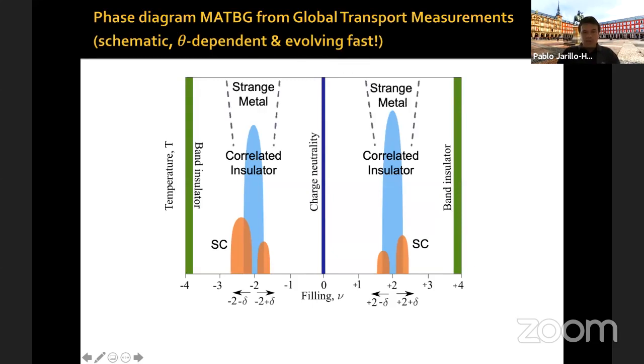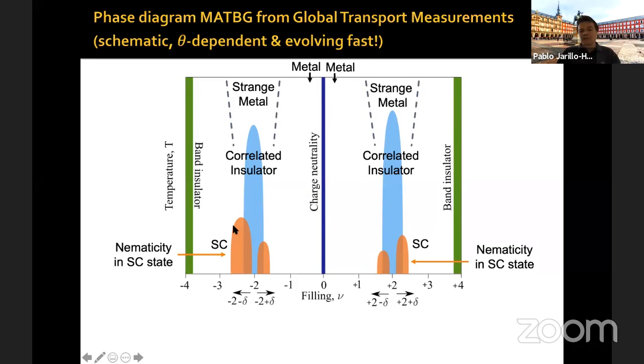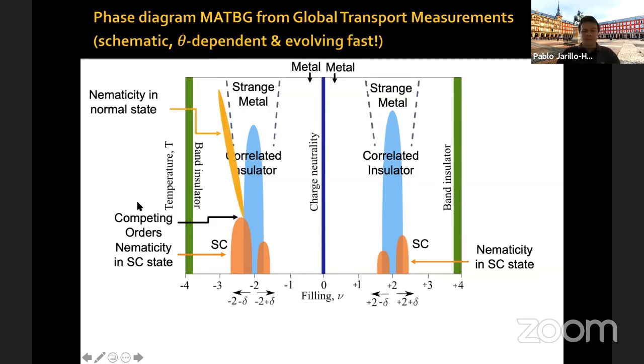So one thing that happened is that in this region around the correlated insulator state, we and others have demonstrated that there is strange metal behavior, whereas closer to charge neutrality the behavior is more regular metal. We also find that the superconducting state exhibits anisotropies, consistent with a nematic superconducting state. We have also measured competition between superconductivity and other orders in the system, which also lead to anisotropies in the normal state of the system. And there's also nematicity in the normal state, as I just mentioned.